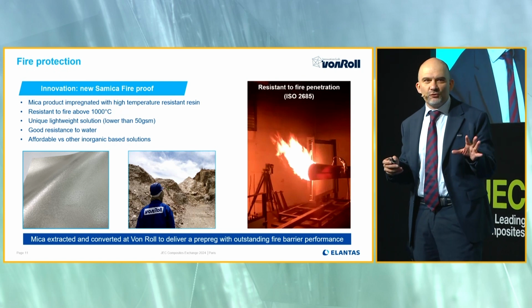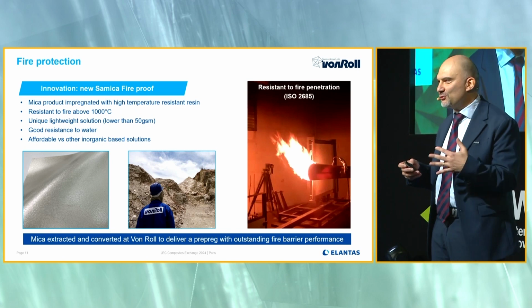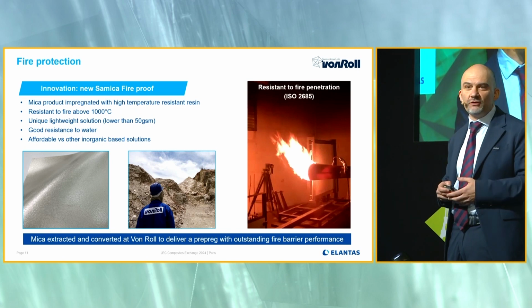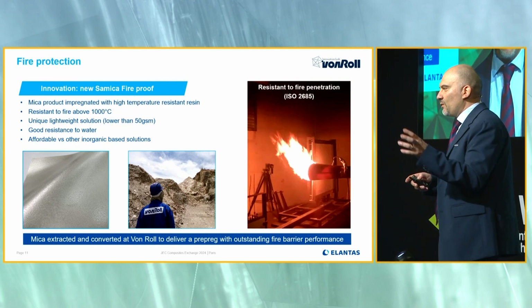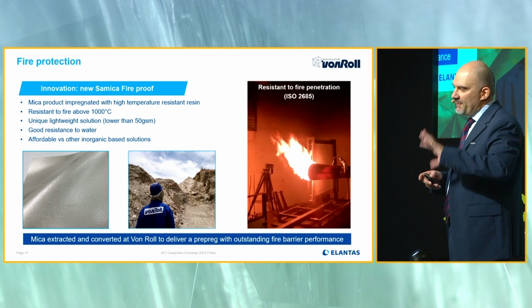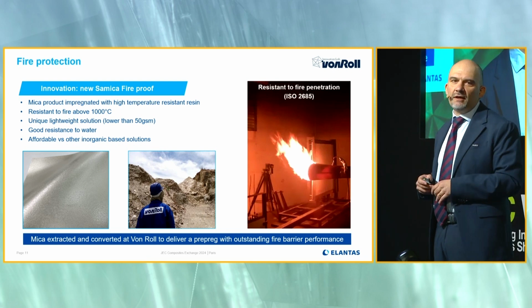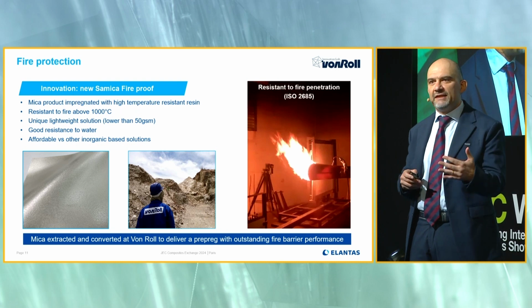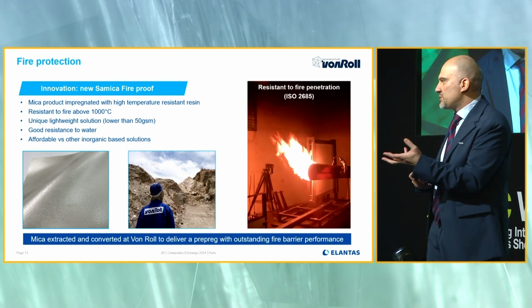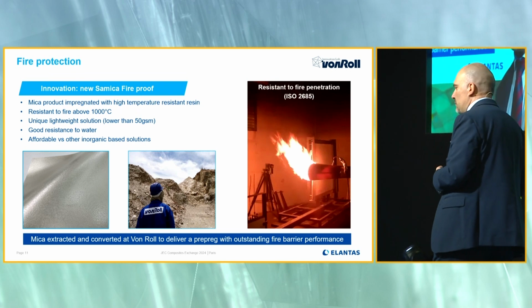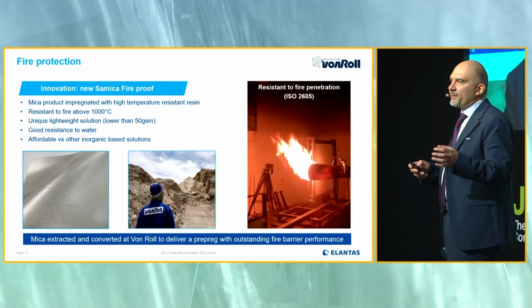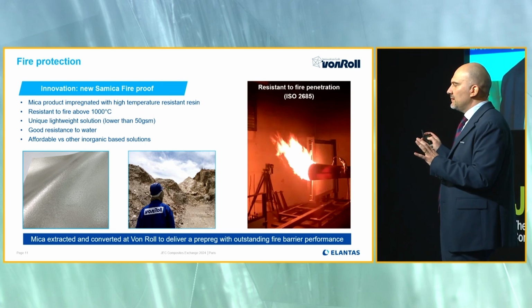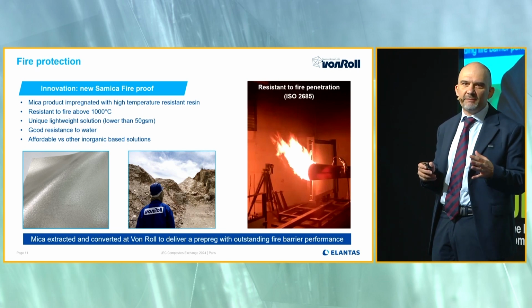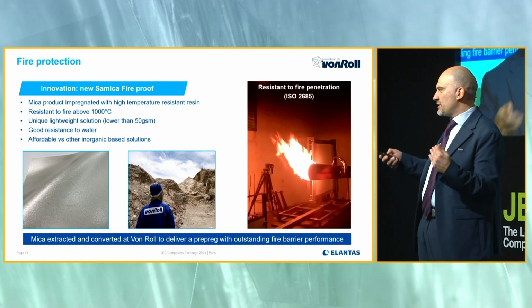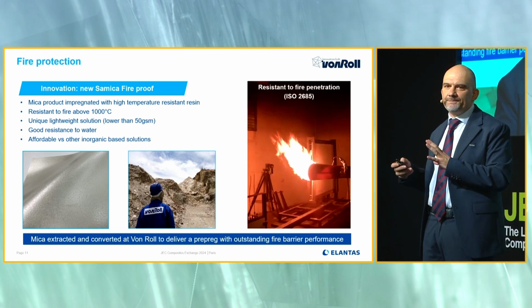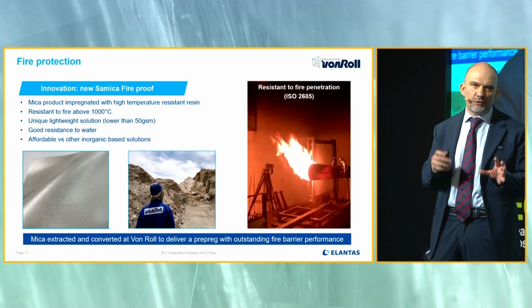So when it comes to this work, I'm proud to show one example of one of the key innovations we have made in the last years. It was not obvious, because it's a special material that was never really used for such applications, but it found in fire resistance the key value proposition for a new product. That is a product which we call the Samica Fireproof. Fundamentally, this product is mica. Mica is a phyllosilicate material which is impregnated with high temperature resistant silicone. And this material can resist about 1,200 degrees.